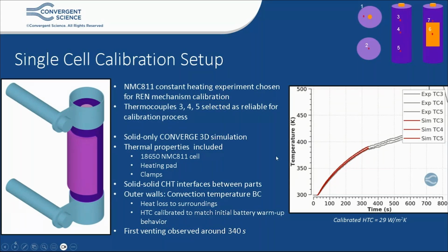If we continue to run the case, we notice that the results start to deviate even at lower temperatures. We went back to the experimental images and experimental movies, and we found out that at around 340 seconds, we got our first venting event. Due to the first venting event, you will notice in your experiment evaporative cooling inside the battery, which will lead to a drop in thermocouple predictions.